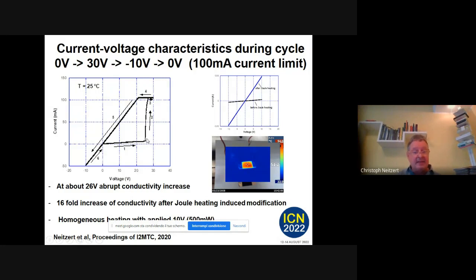So we applied in the beginning a very high electrical power, which was too much for this resistor. In this way, it modified, but it modified in a positive way. I said it was breakdown, but it enhanced the conductivity. This is before Joule heating. This is after Joule heating. And you see, it's perfect again, up to 10 volts, and we can measure this very often. So we had a kind of 16-fold increase of conductivity.